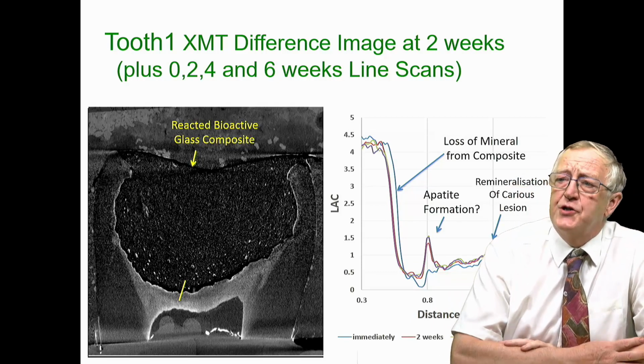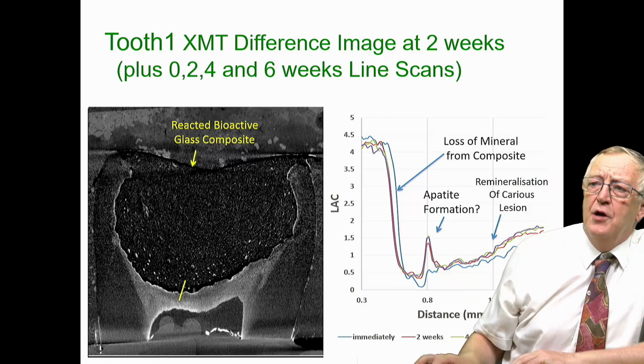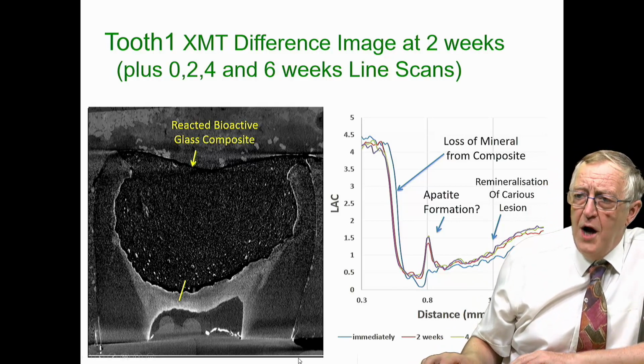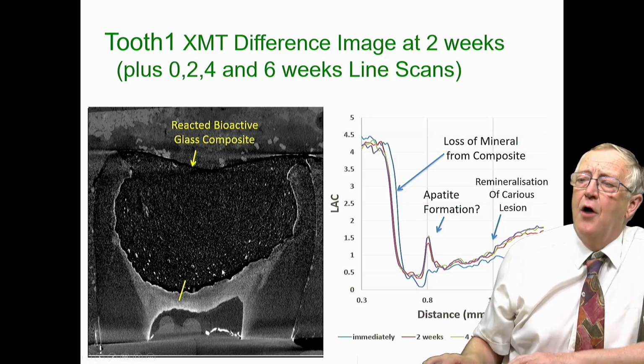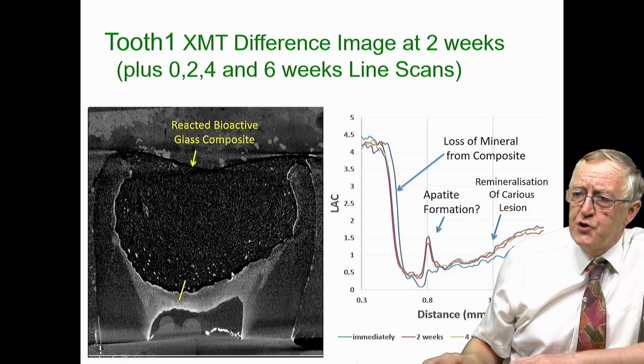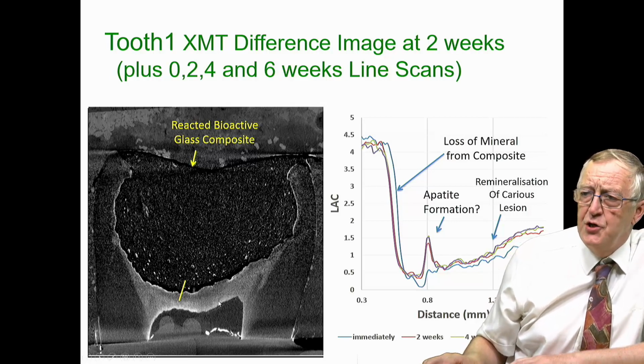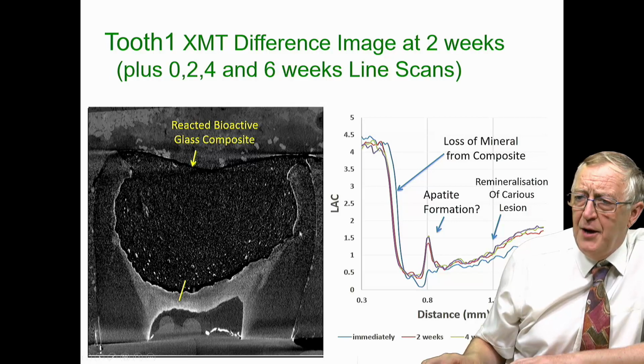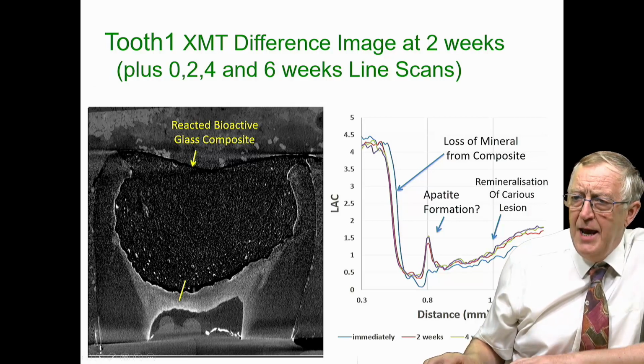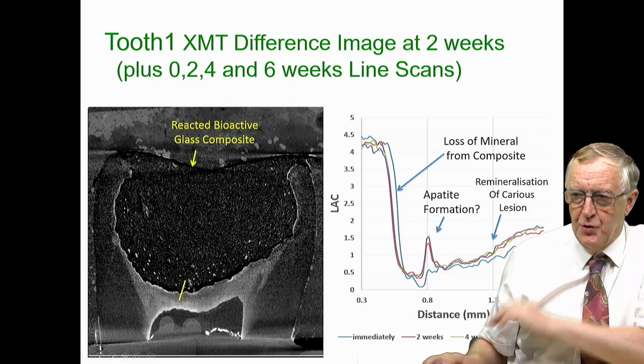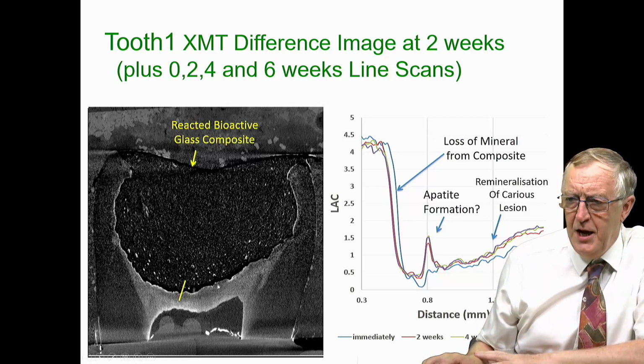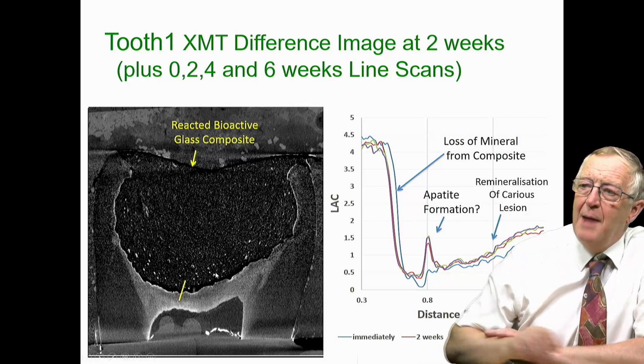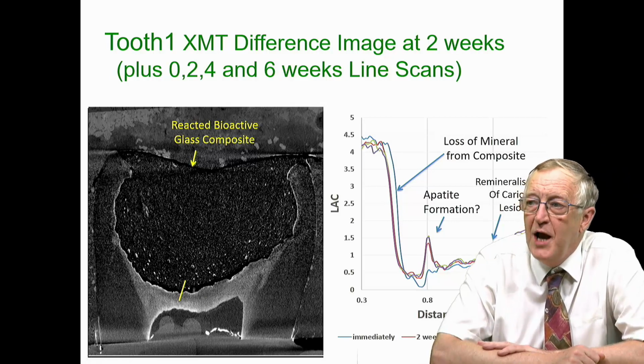So we're subtracting the first image from the last image, and the areas that are whiter are where we've got an increase in mineral content, and the areas that are darker are the areas where we've lost mineral. So you can see we've lost mineral from the bioglass particles in the composite surface. We've increased the mineral content in the carious lesion. You can also see a white line down here and a little bit of one here, which is apatite formed in the marginal gap, and you can also see the apatite formed here. You can also see that we've formed apatite in the bubbles that we had in the composite.